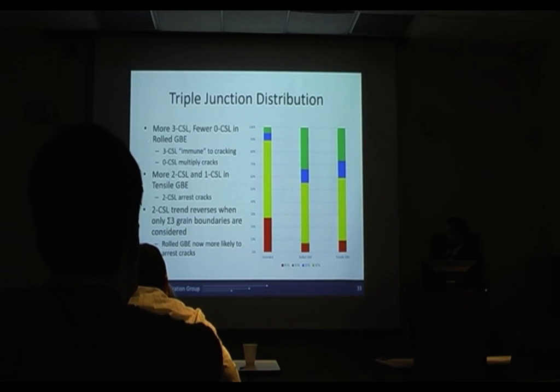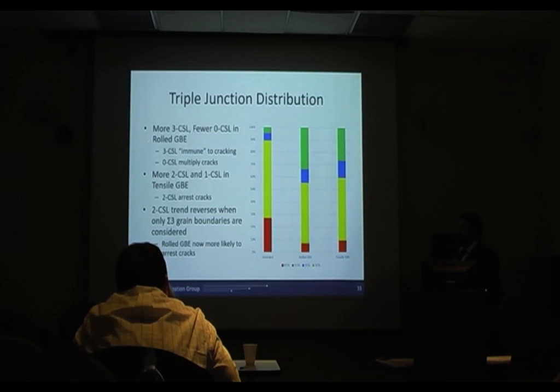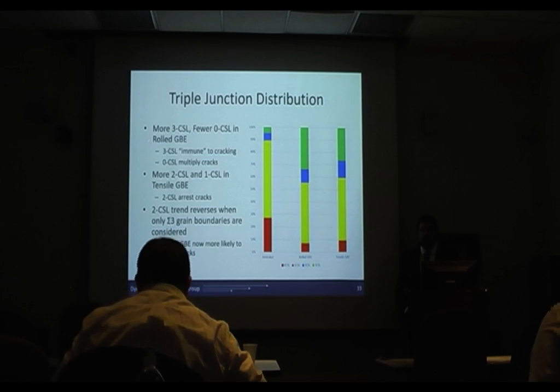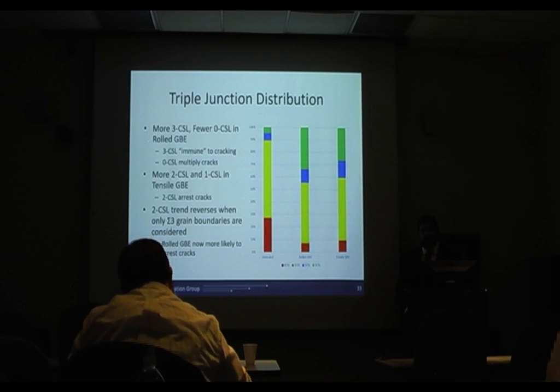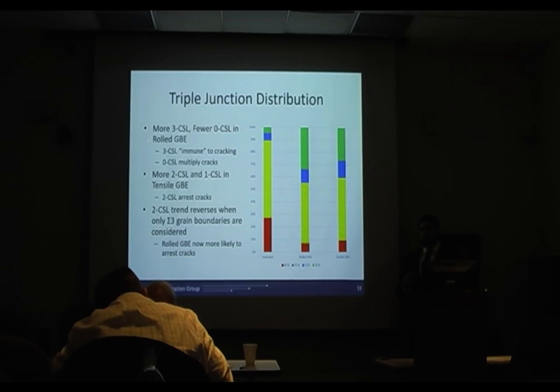The 2 CSL, on the other hand, was higher in the tensile GBE. This is important because the 2 CSL can actually theoretically arrest cracks. So if you have one traveling along and that runs into a triple junction with 2 CSLs, it can stop. However, this trend does reverse if we only consider the sigma 3s to be special, and then the rolled is more likely to arrest cracks as well.